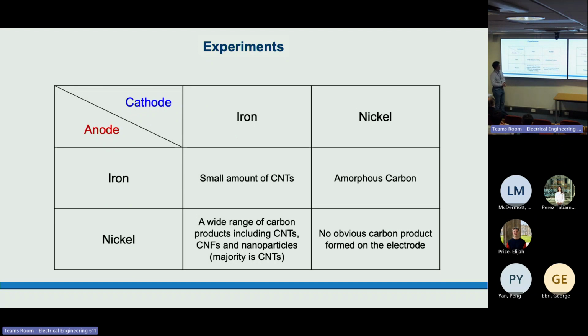The best performing one is when we use iron as the cathode and nickel as the anode. A wide range of carbon products were observed, including carbon nanotubes and also carbon nanofibers, and also other carbon nanoparticles. But the majority is carbon nanotubes. If we use nickel as both cathode and anode, no obvious carbon products formed on the electrode.